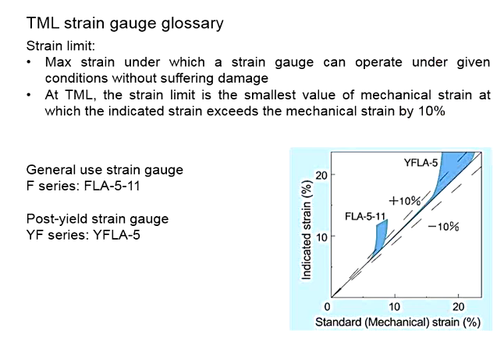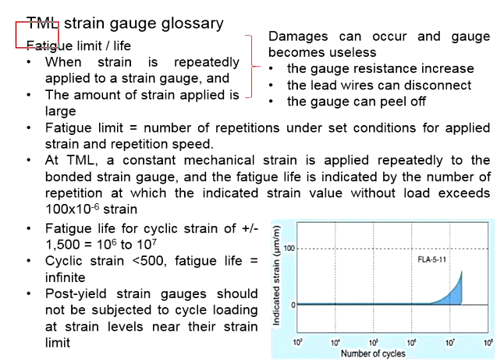Now, if you wish to measure the carbon steel after yielding, then you will need to use the YF series, as this strain gauge can go beyond 10% mechanical strain. That's why you need to know about the strain limit. Next, we talk about the fatigue limit or fatigue life. You know, fatigue load is related to repeated load over numerous times. Now, when strain is repeatedly applied to a strain gauge, that means the strain is applied on and off, and the amount of strain applied is relatively large, damage can occur and the strain gauge becomes useless.